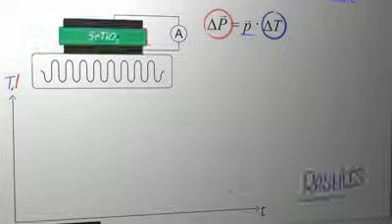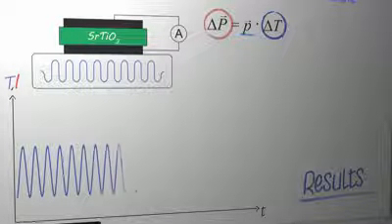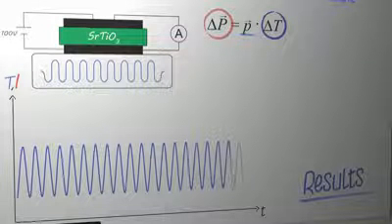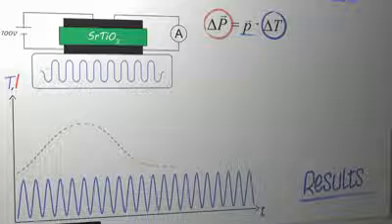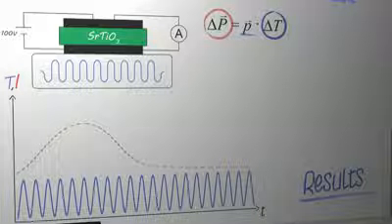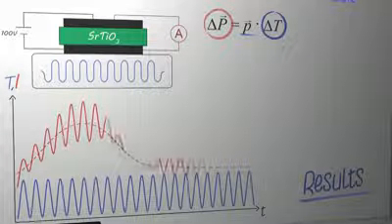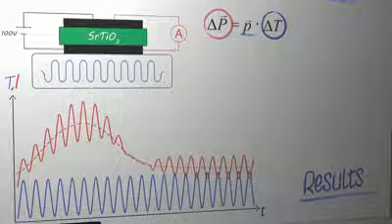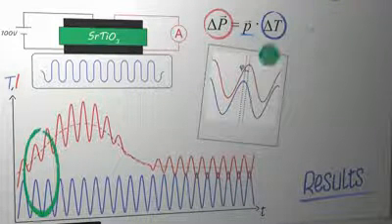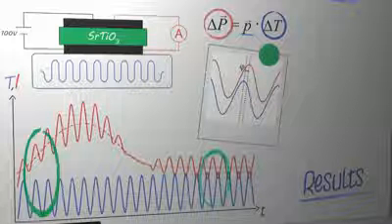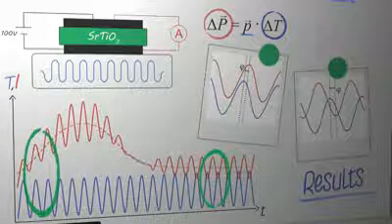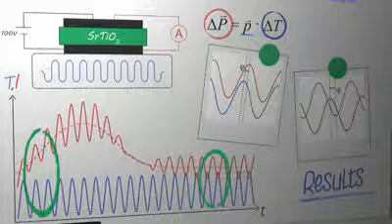This principle is now adopted to strontium titanate, involving the sinusoidal temperature stimulation and simultaneously applying an electric field. The time-dependent forming current of a strontium titanate single crystal is composed of ionic and electronic parts, which are caused by oxygen vacancy migration but are now superimposed by an additional current because of the sinusoidal temperature excitation. At the beginning of the electroformation, the oscillatory thermal current shows an in-phase temperature behavior. When the overall current signal is declining, an out-of-phase current contribution can be detected, revealing the pyroelectricity of the formed MFP phase.